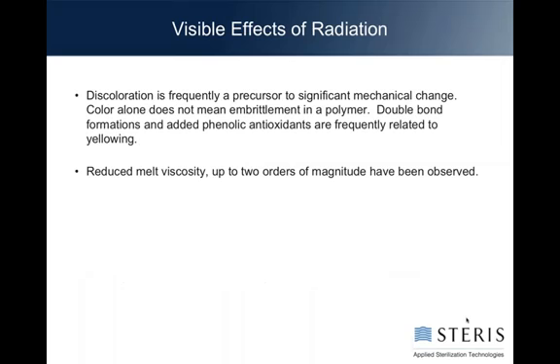Okay, the visible effect is that discoloration. This is frequently a precursor to significant mechanical changes. Color alone does not mean embrittlement in a polymer. Double bonds formed and the addition of phenolic type antioxidants are frequently related to yellowing. Those additives may be the thing that's yellowing, not necessarily something physically changing with the plastic. But remember, they're in there, and they will always be in there.